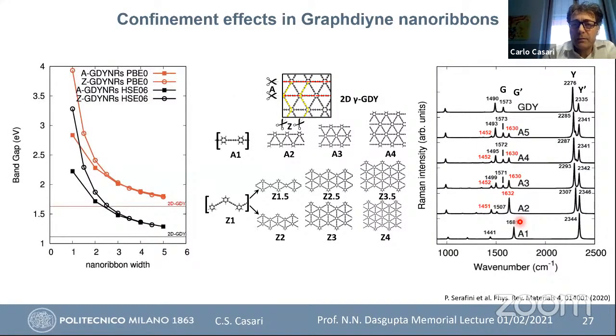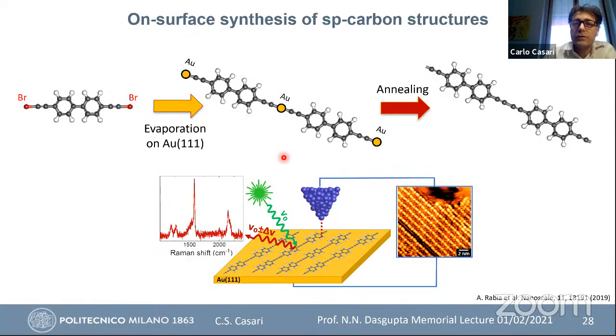Of course, by confinement in graphdiyne nanoribbons, you can play with confinement to tune the band gap, for example like this, in armchair or zigzag structures made by graphdiyne, and also the Raman should be able to distinguish between the different structures. In particular, for this smallest nanoribbon, we were able to experimentally produce something similar by the so-called on-surface synthesis.